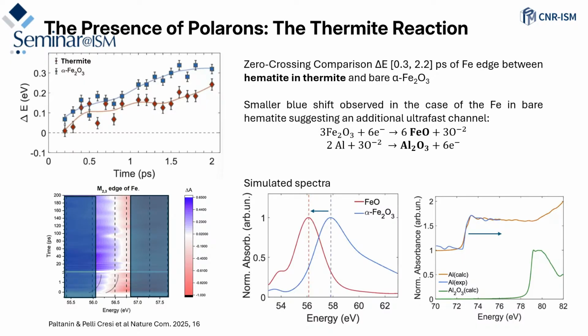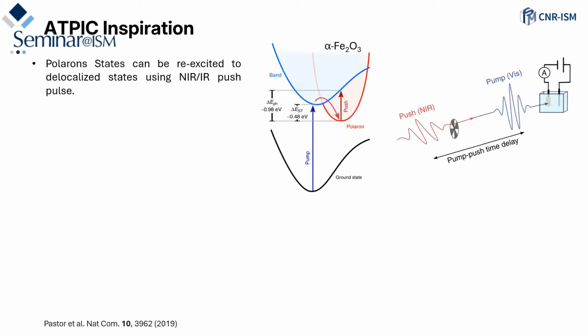So if we have the reduction of the iron oxide, the hematite, to FeO, we should have a redshift. Probably what we have here is just two different channels. So we have the formation of polaron, and contemporarily we also have the reduction of hematite. So in this case, polaron is just a fingerprint that something is happening. Something else is also happening, so we also have this reduction.